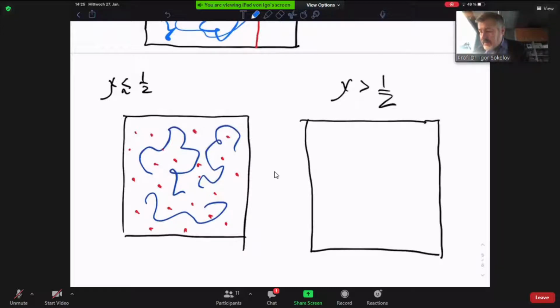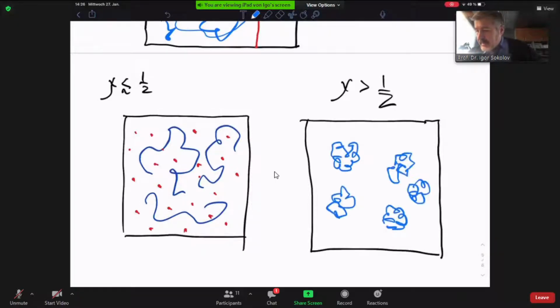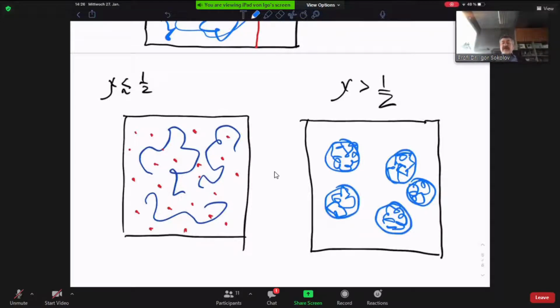They are essentially repelled from the solvent molecules, or if you want, the solvent molecules are repelled from the monomers. And the monomers in a polymer make a kind of a droplet, which are called globules. So now we have these globules. Within each of them, there are hardly any solvent molecules inside. So now I have an ideal gas of globules, essentially.